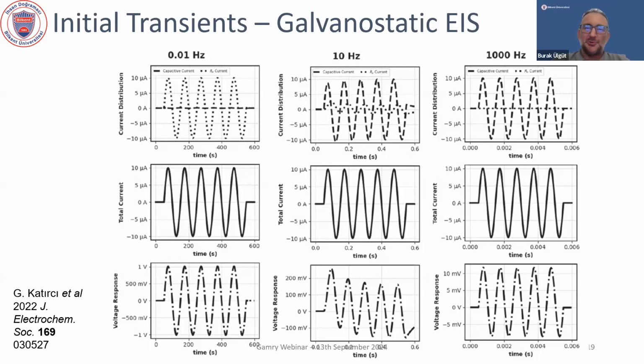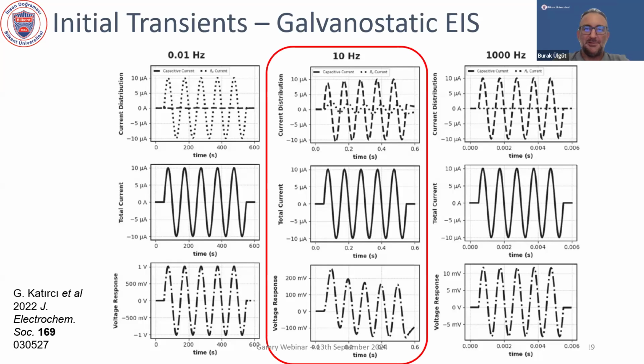When the current goes through the capacitor, it is pretty steady. When the current goes through the resistor, it's pretty steady. It is right around this resonance frequency that the current is crossing over from one to the other, right in this middle panel. You can see that actually the voltage is first dominated by the capacitor a little bit, and then it starts getting dominated by the resistance. When it's dominated by the capacitor, it's more asymmetric. When it's dominated by the resistor, it's more symmetric. And in the middle, it is crossing over from one to the other.